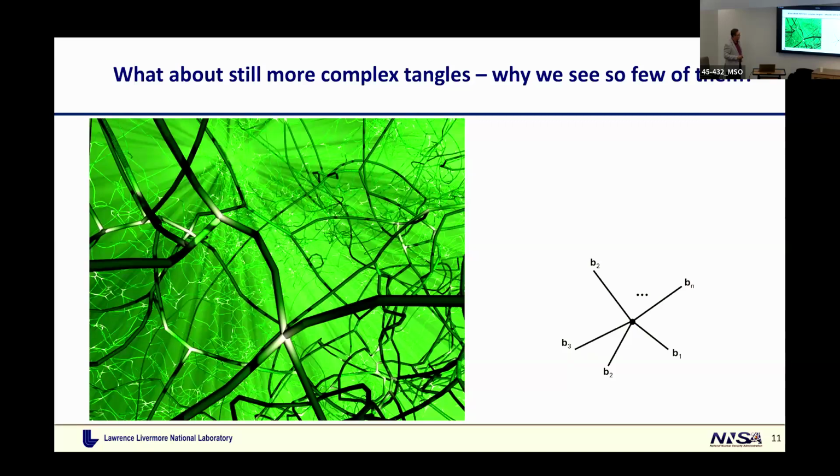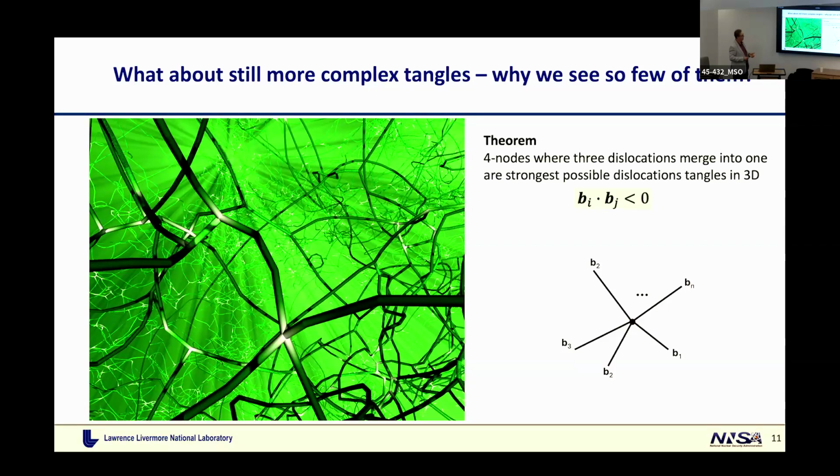And we then observed something also quite interesting. I said that most of the elements of this network are 3 nodes. There are occasional 4 nodes. But for some reason, we almost never see 5 or 6 nodes. So why is that? We kept looking, and later proved the theorem that it's actually a fundamental property of three-dimensional space: only 3 nodes and 4 nodes can be mechanically stable. 5 nodes and 6 cannot be.